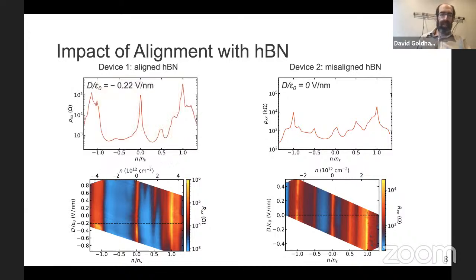In contrast, in the aligned HBN case, the resistivity is 100 kiloohms, and that's higher than 20 kiloohms. It's too high to get in graphene without breaking some symmetry. And so that tells you something strange is happening. In addition, there are features that are not at simple multiples or simple fractions of filling. So filling 4 represents 4 electrons per moiré cell, and here -4 electrons per moiré cell. And you can see that there are extra features outside here. Those turn out to be related to the density at which a graphene boron nitride moiré is filled. So there are some indications that something's a little bit strange here.